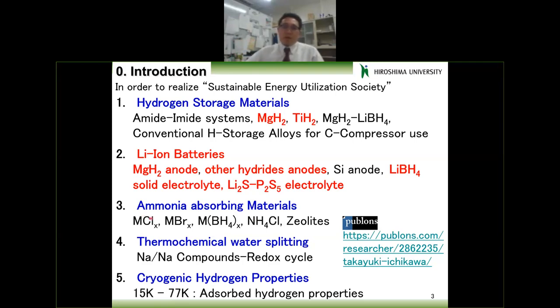We also focus on thermochemical water splitting by using a quite untypical sodium compound redox cycle. Only we are focusing on this material, but by heat alone, below 500 degrees C, we can get hydrogen and oxygen from water using this cycle. We also focus on cryogenic hydrogen properties. We noticed some adsorbed state at such a low temperature, about the liquid state of hydrogen. That adsorbed state is quite interesting: it has normal molecular properties, but also some quantum effect. So we focus on these cryogenic hydrogen properties.